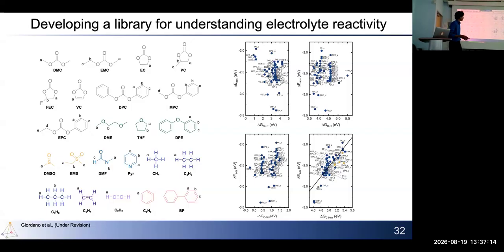Why is that interesting? Because this adsorption energy takes a whole lot to compute — you have to develop the surface, understand the reaction, figure out the reaction sites, and then get the adsorption energy. But with this simple descriptor, you don't have to model a surface at all. You just have to model the reactivity of the gas phase molecule itself, which gives tremendous predictive power without having to compute surfaces, just the reactivity of molecules in the gas phase, which is orders of magnitude cheaper computationally.